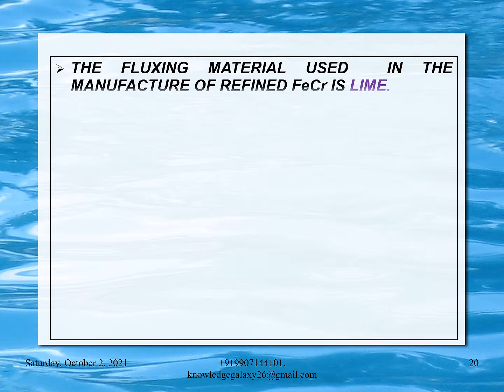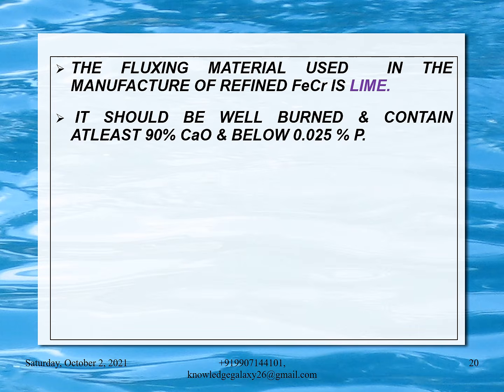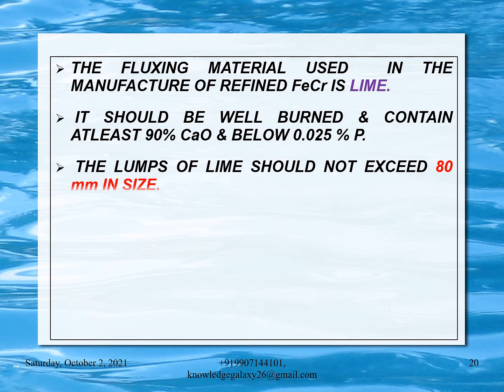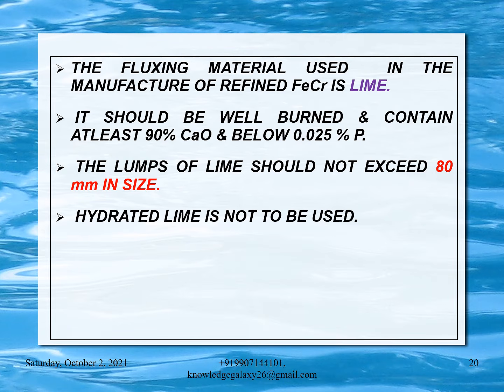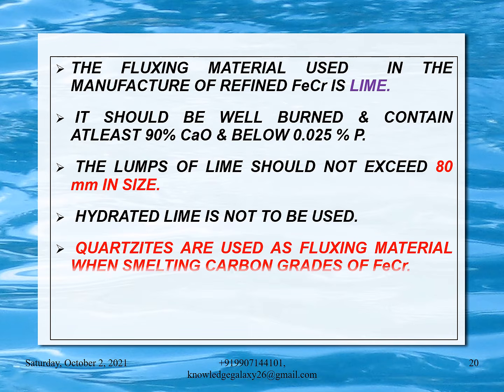The fluxing material used in the manufacture of refined ferrochrome is lime. It should be well burnt and contain at least 90% CaO and below 0.025% phosphorus. The lumps of lime should not exceed 80 mm in size. Hydrated lime is not to be used. Quartzites are used as fluxing material when smelting carbon grades of ferrochrome.